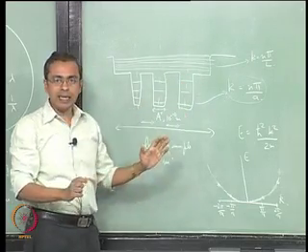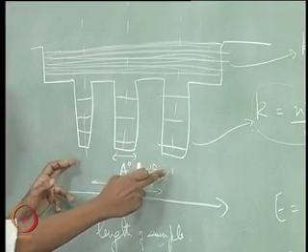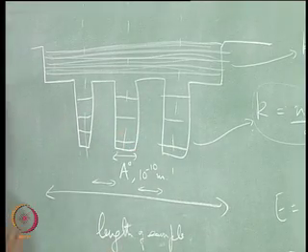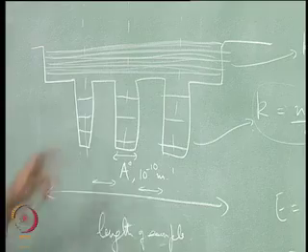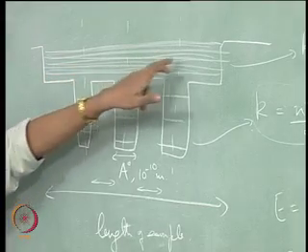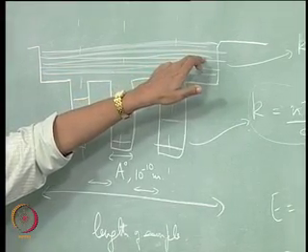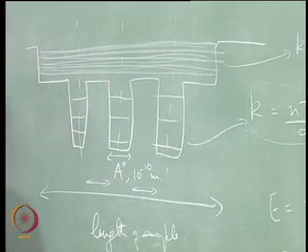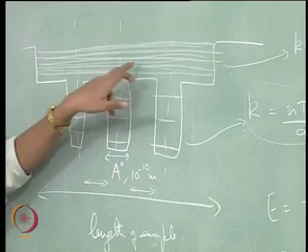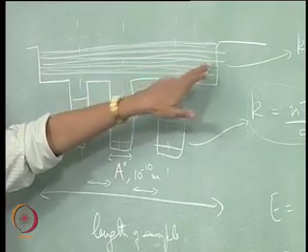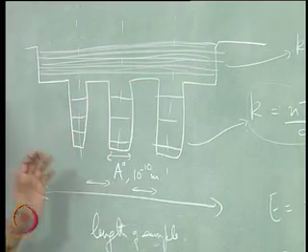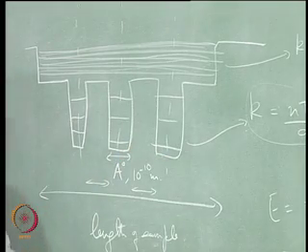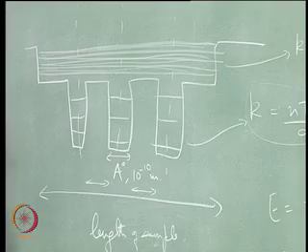So what we really need is a reciprocal lattice depiction of this structure. In that reciprocal lattice depiction we will plot the allowed wave vectors of this electron. From what we have looked at so far, what we will find is that when the wave vector of these electrons touches the Brillouin zone of the structure defined by this spacing here, diffraction will occur. Okay, so that is the key idea.